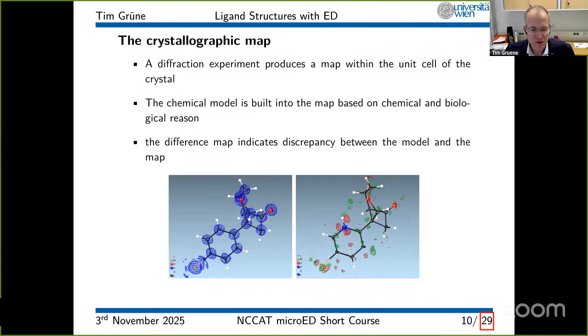This is a small molecule structure, so we have very high resolution data. For proteins, this may vary a bit. Again, it's important to get a feeling of your structure. What I usually do is I change something deliberately where I know it should be right. If, for example, for a protein structure, you know there should be a helix, you can delete a couple of residues there, do the refinement and look at the effect, and then you get a feeling of what your data really includes.